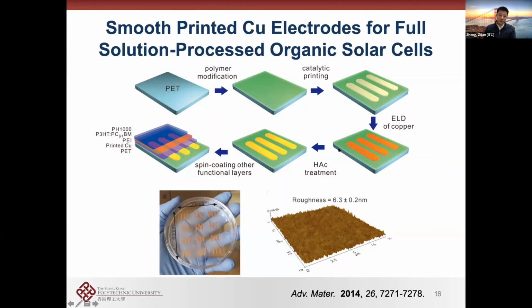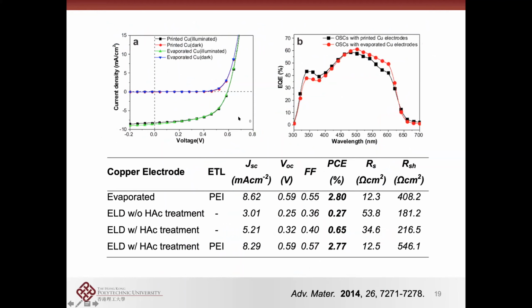But in our case, if you do it with PAM, the conductivity is no problem, as I demonstrated before. The roughness is very low as well, about 6 or 7 nanometers, which is very close to the substrate roughness. And therefore, we can use this low roughness electrode as a bottom layer of opaque electrode, and then you spin-coat whatever materials on top to finish the entire device, right? So then we can come up with a device with a very similar performance compared to those devices fabricated through evaporation and vacuum technology, right? Very, very similar result. This was an organic device.